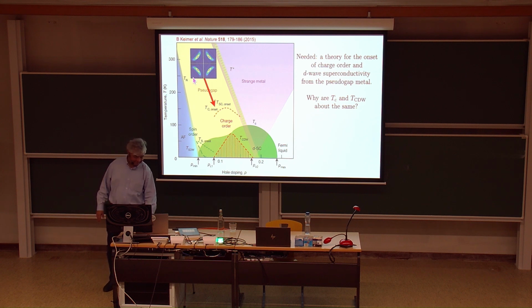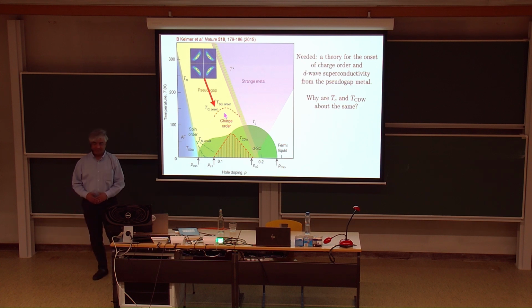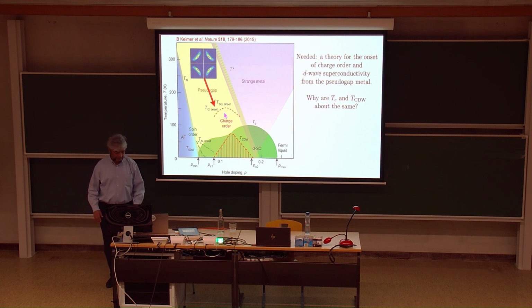This Tc is coinciding with this TCDW, and the onset of fluctuations that you can see in different measurements: diamagnetism for superconductivity, X-ray scattering for charge density wave, all roughly happen around the same temperature. And from the point of view of Fermi liquid theory, this is highly surprising. There's no reason at all for these two instabilities to be even roughly the same. They're determined by very different types of interactions, and why should they be the same?